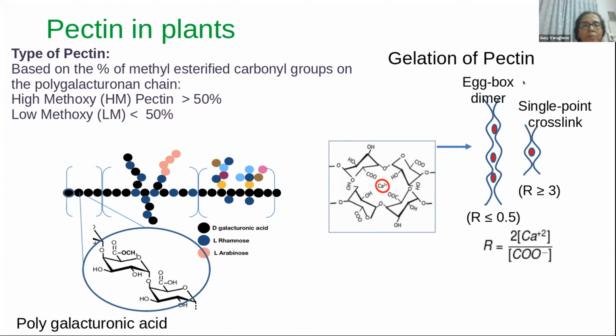The pectin we have used for our experiments is something that we see normally in plant cell walls, which is known as the low methoxy pectin, which means its methyl esterified carbon groups are less than 50%. There is a high methoxy version of the pectin also, which is also found in plants, and they do undergo changes using an enzyme, methyl esterase. It can actually go from high methoxy to low methoxy, and vice versa.